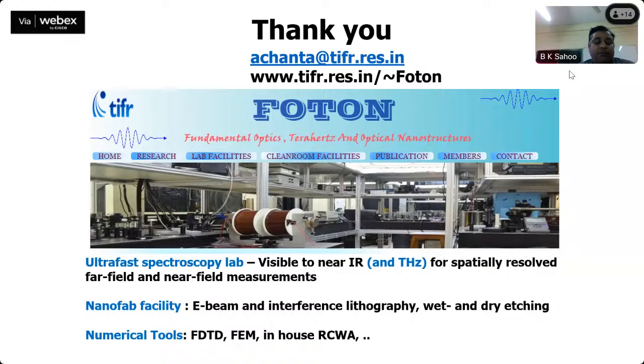Right. First thing is, if you take metal disks, as I showed, for atom trapping, what we showed is that the minimum of the trap happens at about 20 nanometer for gold and about 12 nanometer for silver. So one obvious question is that if the plasmon mode resonance for the metal nanoparticle and metal layer interface is there, then it's going to contribute to the decay of the atom which is so close by. So what are the dynamics? Is it really the right structure? It needs to be checked. My supposition is that possibly there will be an effect because 20 nanometer is too close.